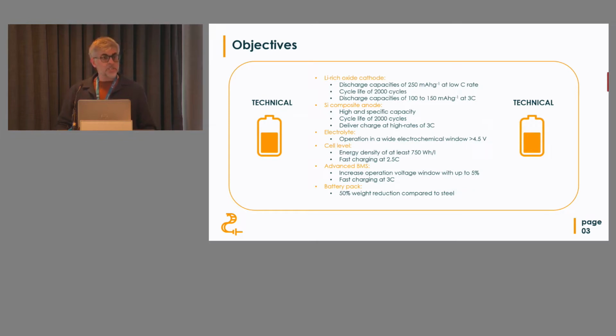We have similar objectives for the anode, which is a silicon graphite composite. So we are looking at high capacity, high cycle life of 2,000 cycles, and also being able to release capacity up to 3C. This is complemented with an electrolyte to ensure SEI and cathode electrolyte interface formation at both electrodes and to perform stably beyond 4.5 volts. At cell level, energy density is one of the main targets, which is 750 watt-hours per liter, together with fast charging.